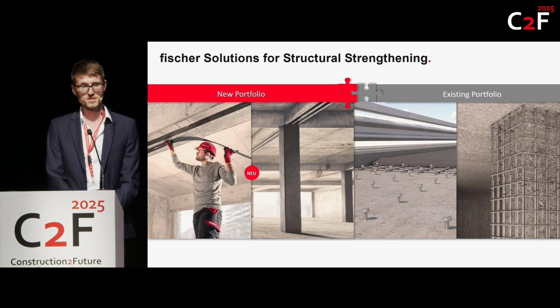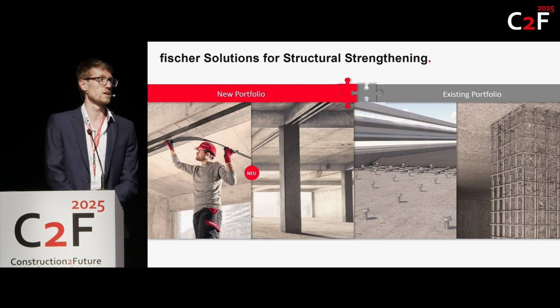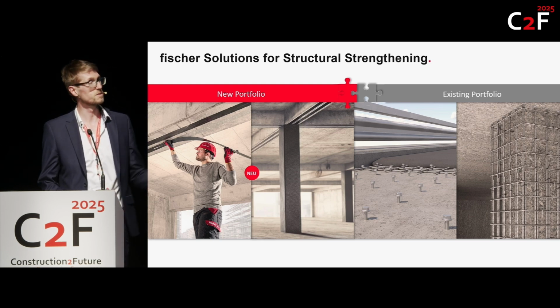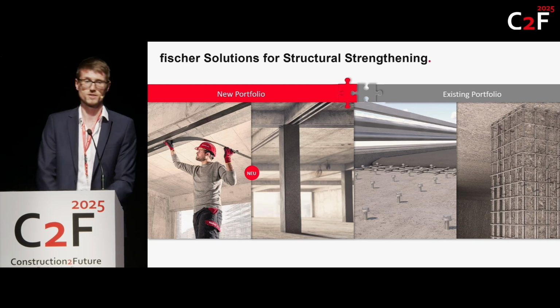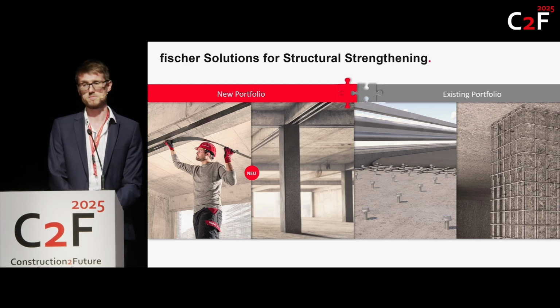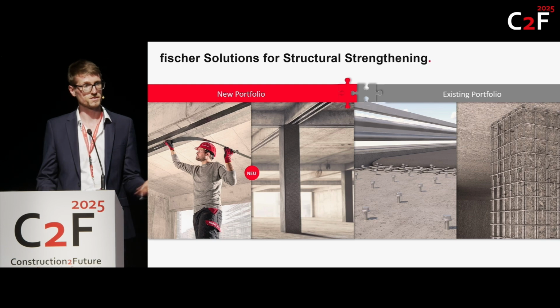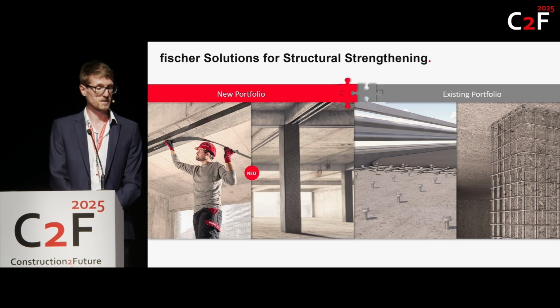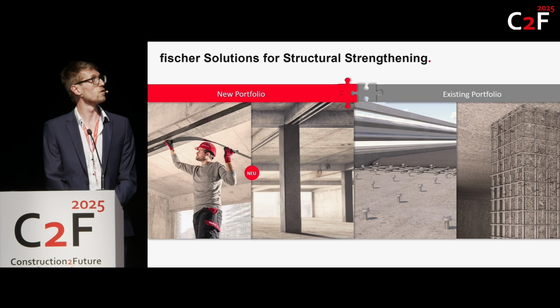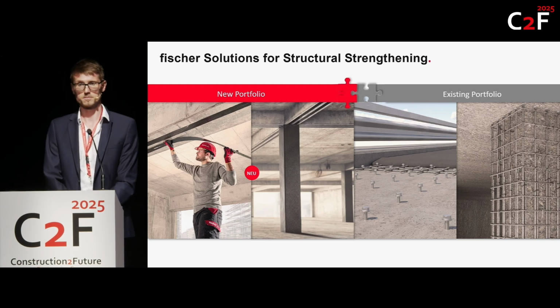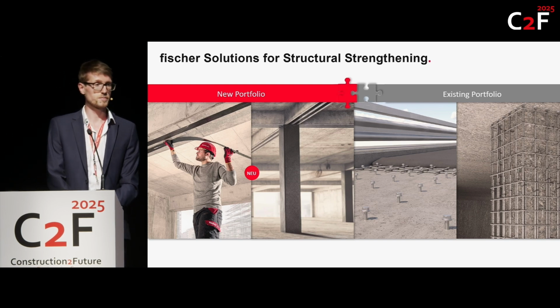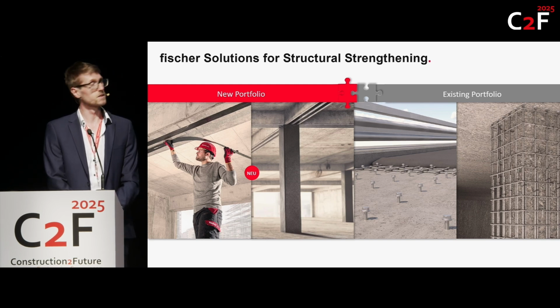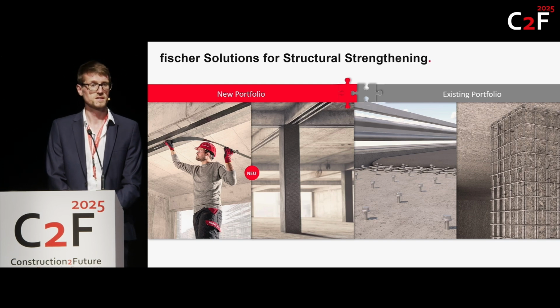We didn't want to decrease the free height of structures, because otherwise, if you do it with post-installed rebar solutions, you increase the cross-section of columns, you actually lose space, which is not necessarily what we want in especially crowded areas and cities. Which is why we came up with a portfolio of CFRP strengthening products. First of all, carbon fiber fabrics, which are really versatile, but a little bit more labor intense. Secondly, externally bonded CFRP laminates and near surface mounted laminates. Of course, they're very different in application and also different in their properties.